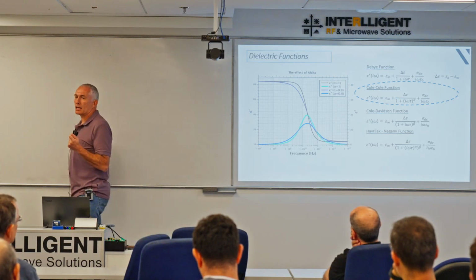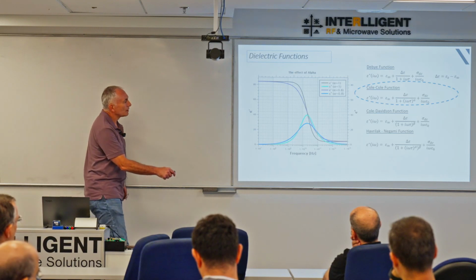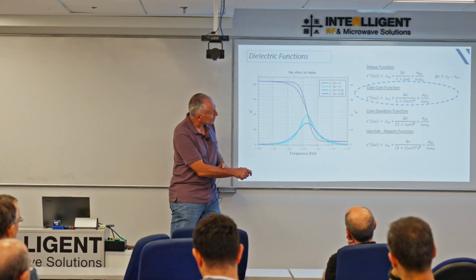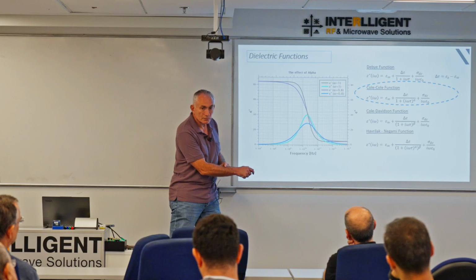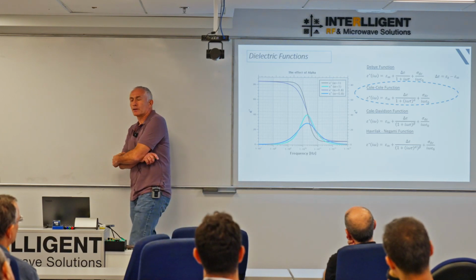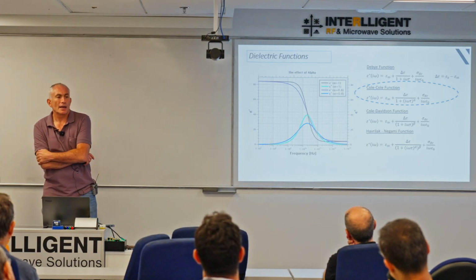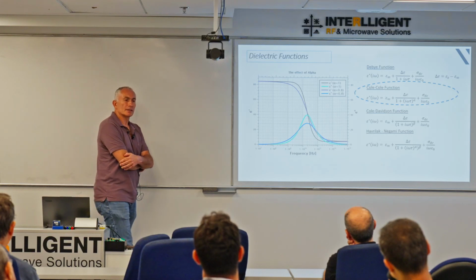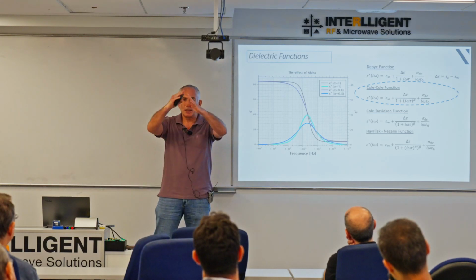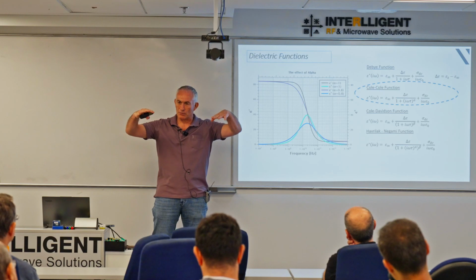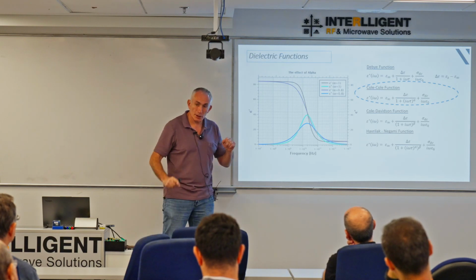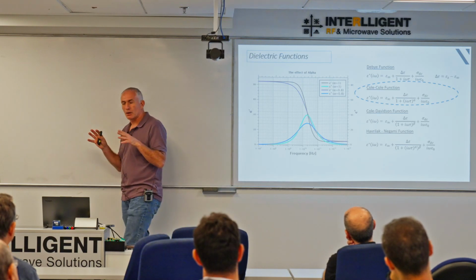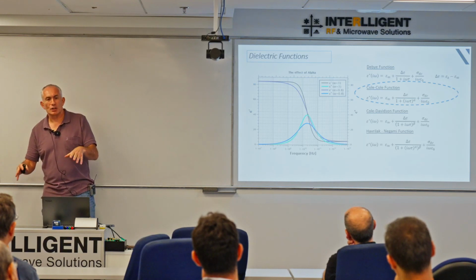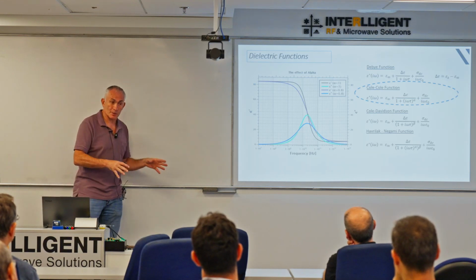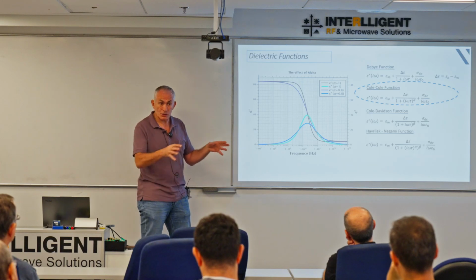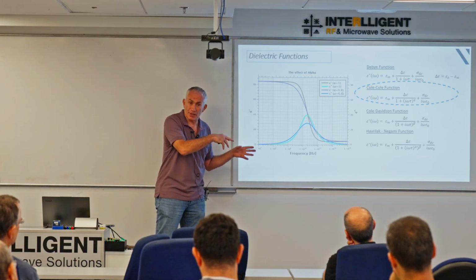By trial and error, they came across this equation here, which could fit that by the addition of an exponent. The exponent alpha goes from 0 to 1, and if it's 1, you have a Debye, and as it gets lower towards 0, your peak will flatten and distribute out more and more. Initially, this was purely a phenomenological explanation of what they were seeing. We now have an explanation for what that actually means, and I'll talk a little bit about that explanation.